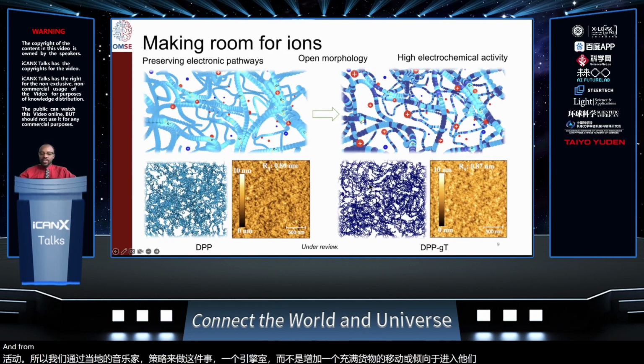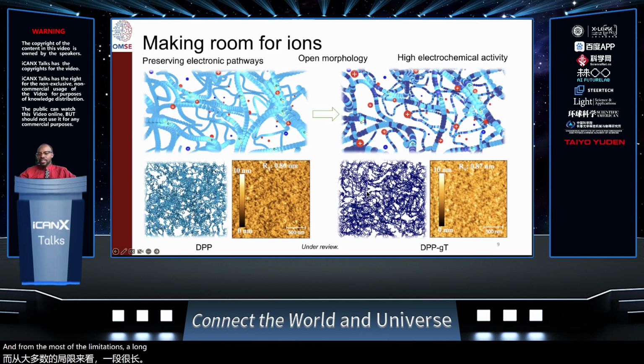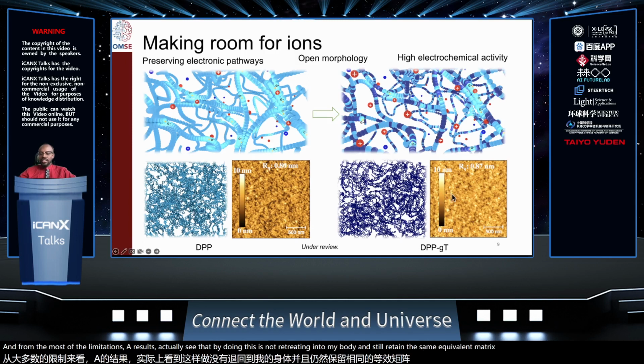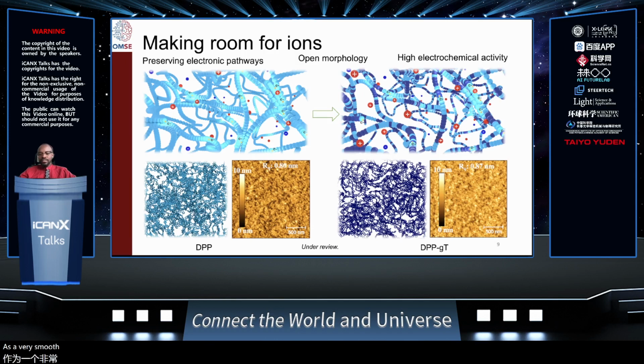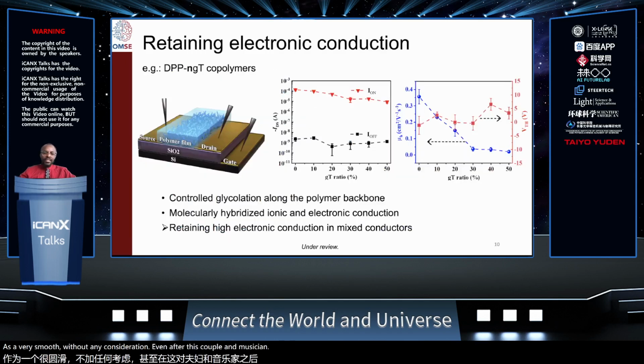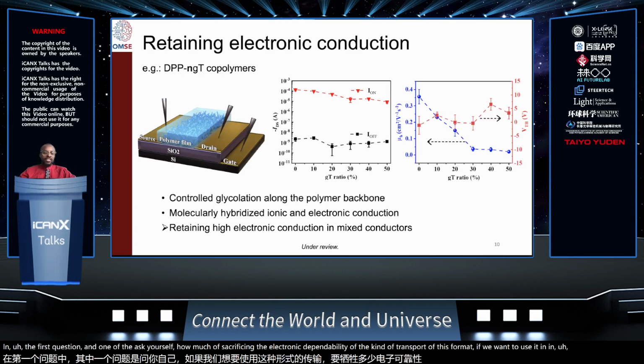And from the molecular dynamic simulation results, we see that by doing this, we're not perturbing its morphology that much. We still retain the semi-crystalline nature. And as you can see from the AFM morphologies, we have very smooth films without any phase separation, even after this copolymerization. The first question we wanted to ask ourselves is, how much are we sacrificing the electronic conductivity or electronic transport of this polymer if we want to use it in transistor devices, for instance?